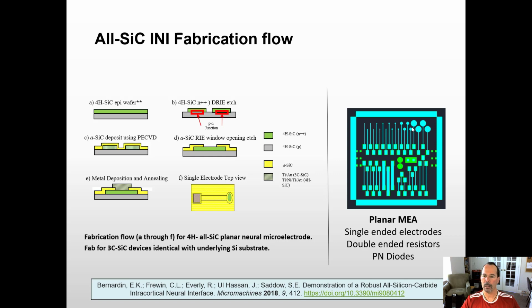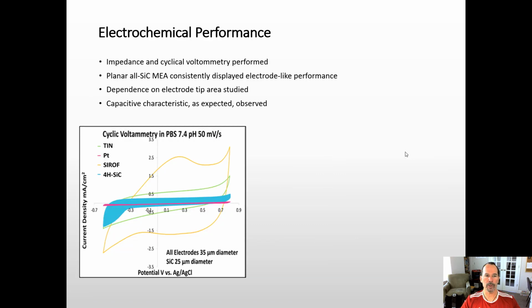We have single-ended electrodes with a different size of recording tip at the end to look at the geometrical surface area and its effect on performance. And we have double-ended resistors to look at resistivity, and some Schottky and PN diodes to characterize the material. So a lot of the data you're going to see today is going to be from this structure here. So starting with the 4H silicon carbide, all silicon carbide device,